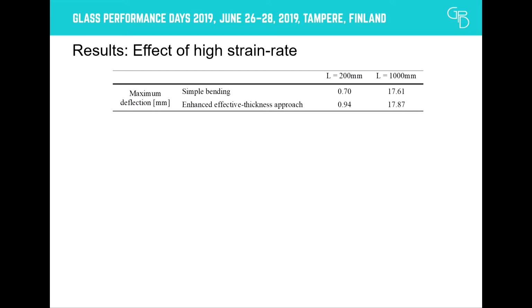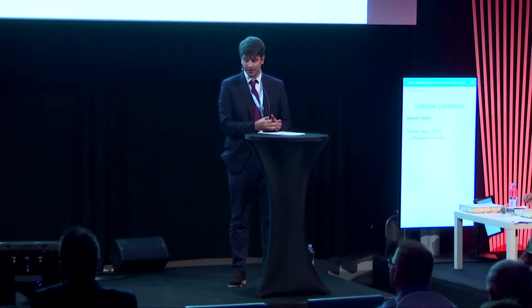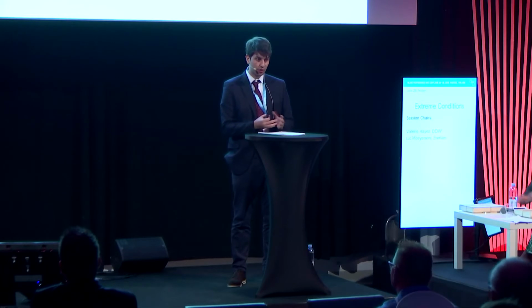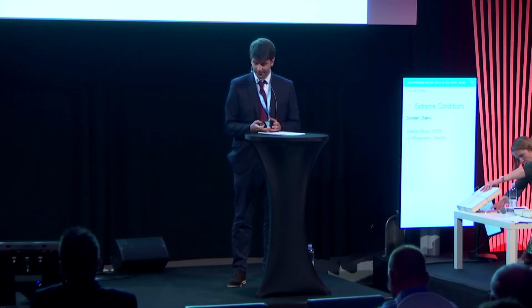So in this case, we compared the deflection under simple bending with the enhanced effective thickness approach developed by Dr. Galuppi and Royer Carfagni. And we found that this is valid for blast design due to the higher shear modulus of PVB, especially for the larger lengths, and therefore shear deflections, as commonly considered in practice, can be ignored.